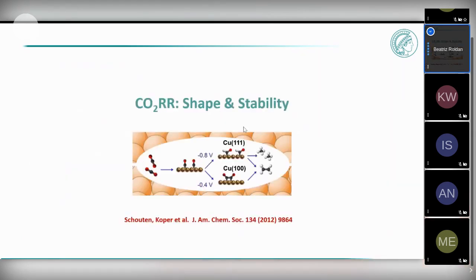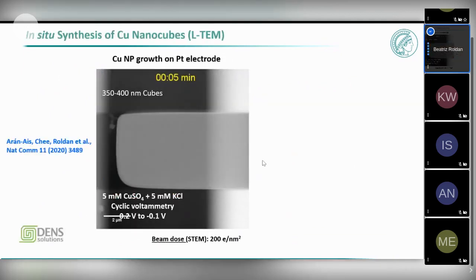To go further, we wanted to look at the role of the particle shape, and there were some interesting previous studies for CO electroreduction showing that if you have 100 facets, you favor the production of ethylene. If you have other terminations, for example 111, you can make ethylene and also methane. So we wanted to make 100 facets on purpose, and we tried to do it electrochemically. I show you here how we synthesize our structures.